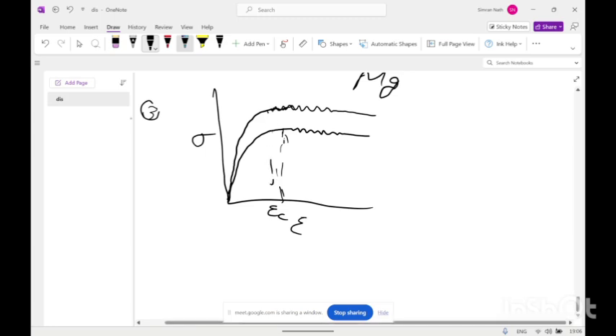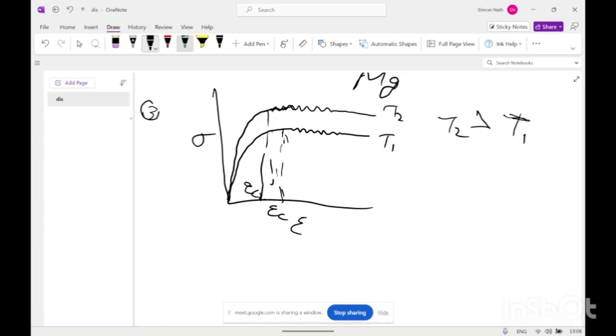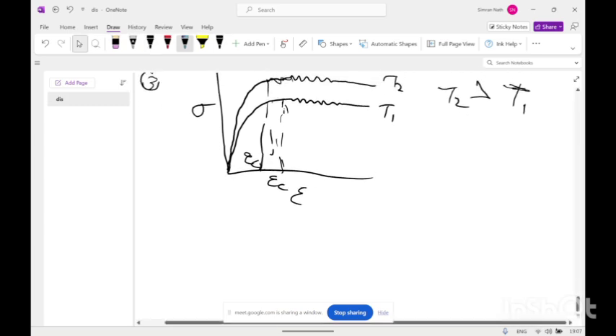So this is the critical strain. So this is T1 and T2. So T2 is greater than T1. So with increase in temperature, the thermal activation is high, and due to the thermal activation, the solute atoms are easy to pin the dislocations. So the critical strain will decrease for higher temperature.